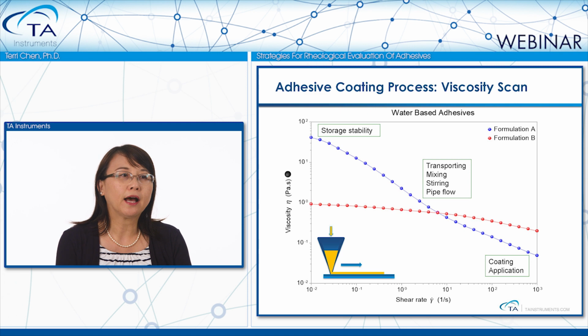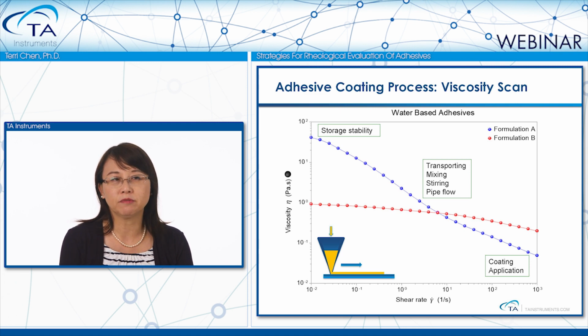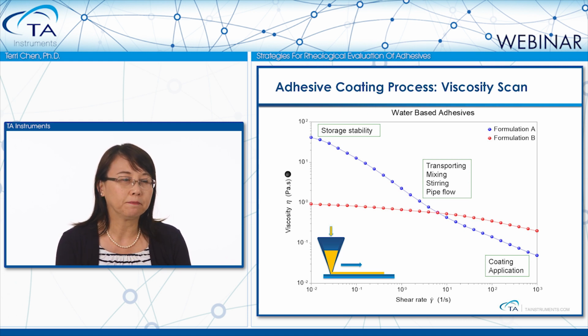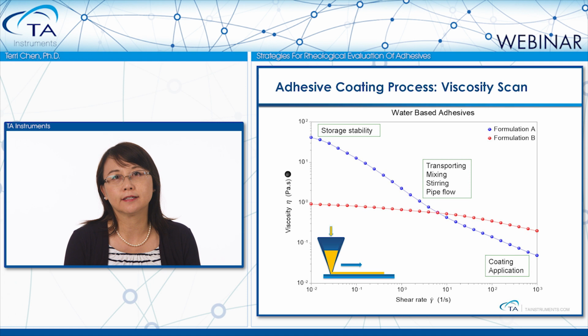Both formulations have similar viscosity at medium shear. But since A is more shear thinning, at the application high shear rate, formulation A shows much lower viscosity compared to formulation B. This means A potentially could spread easily and coat thinner layers.